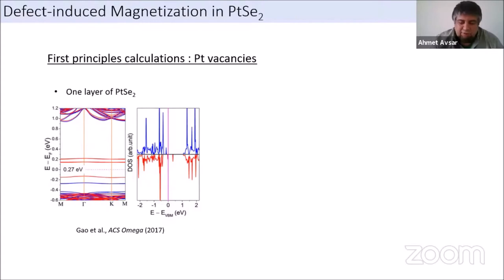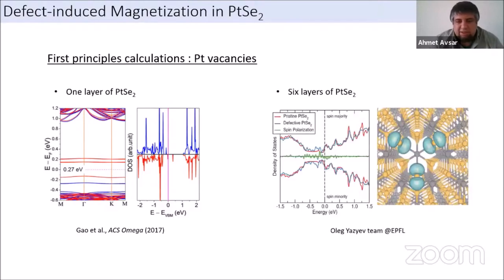As I mentioned before, it was very challenging to get the monolayer to test if this material is really magnetic. So we asked our collaborators at EPFL, Oleg Yazyev's group, to calculate if the thicker layers of platinum diselenide are also magnetic. And indeed, we got a lot of interesting insights which help us to understand our experimental results later on as well. What this theoretical calculation is saying is, yes, even in 6 layers, you do see magnetism, but only if you put these impurities on the surfaces. If you have these defects within the material, basically the magnetism is quenched. That was the first result they got through the calculations.